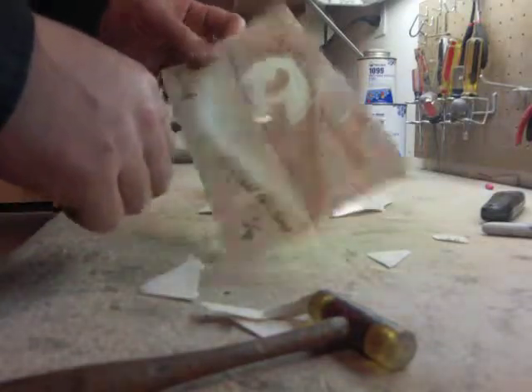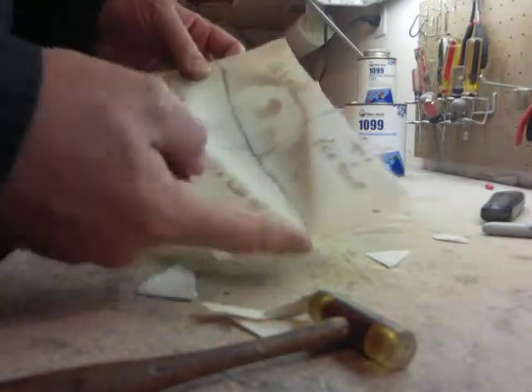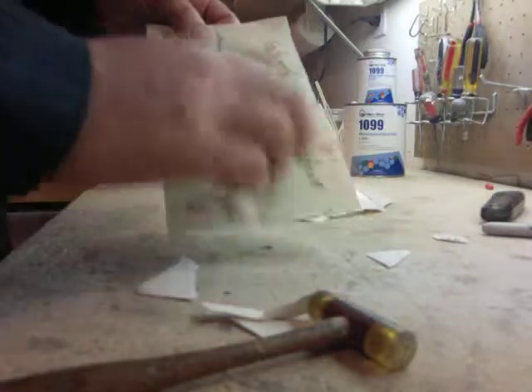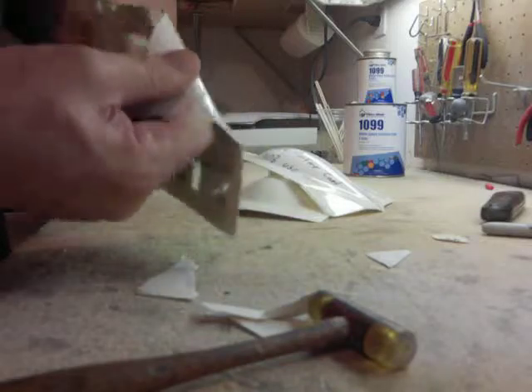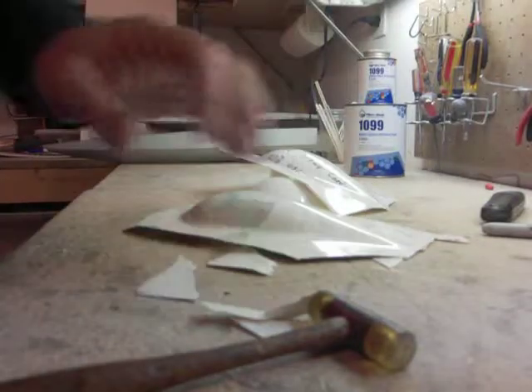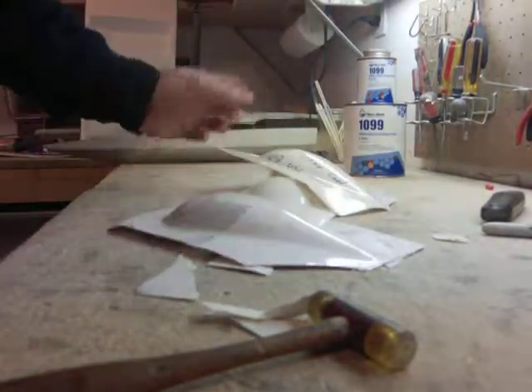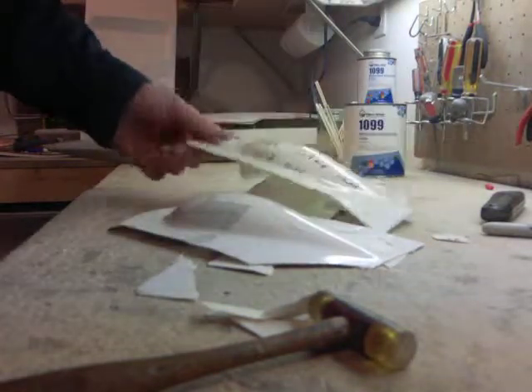So definitely better than the polyester gel coat did with the various treatments on the epoxy layup. That acetone wipe after the green seal, covered with green seal, cured, washed off, wiped down with acetone, really did not separate either. So it looks like you can get a polyester gel coat to work with epoxy, and you can thin the surface coat a little bit. So, never know. I'll post these results and see what the experts think. Thank you.